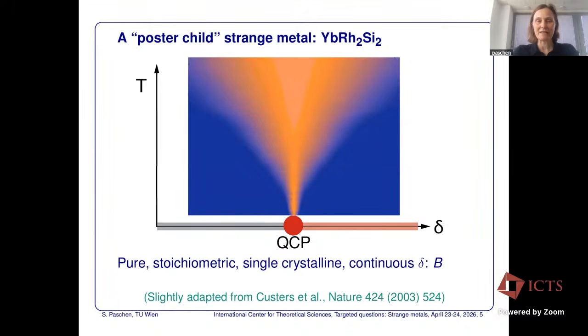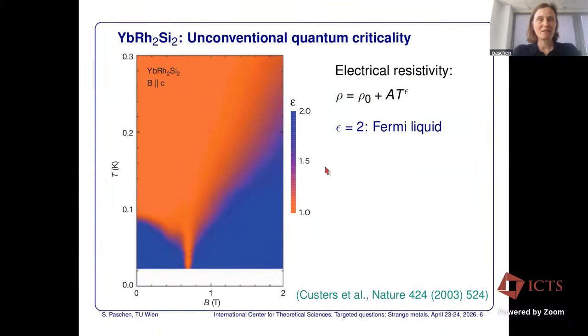It essentially looks like this. It's a little bit symmetrized, but it's almost this. Blue is Fermi liquid, exponent 2, and orange is strange metal, exponent 1 in the temperature dependence of the electrical resistivity. Heavy fermion compounds, or not all, but most heavy fermion compounds, can be made very pure. They are stoichiometric, they are single crystalline, and they frequently can be tuned with a continuous tuning parameter, such as magnetic field for this material. And in that situation, I say the canonical situation is that strange metallicity arises from a point. I showed you the real data here without symmetrization.